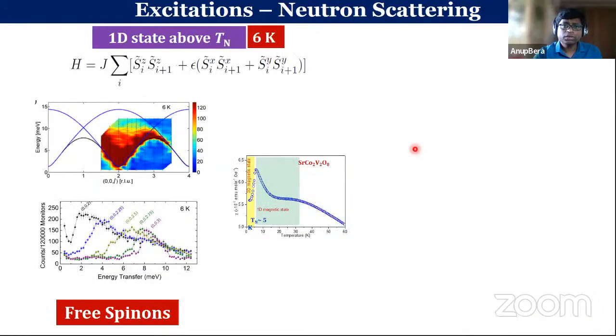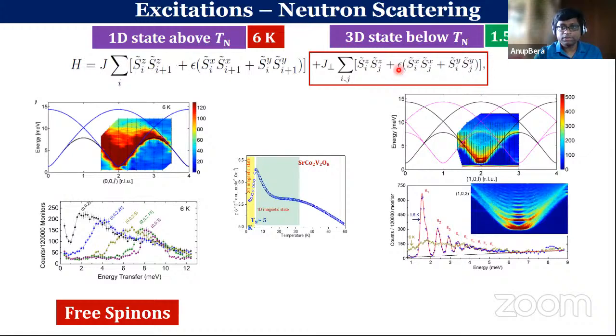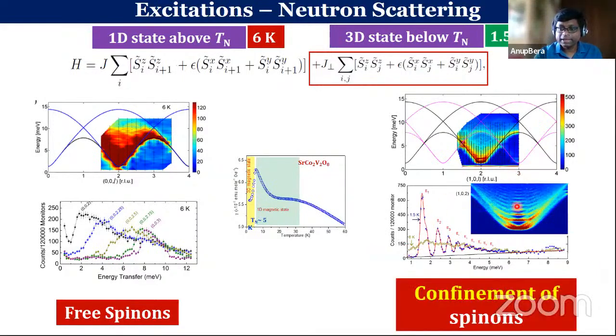Now, if we go below the ordering temperature, in the 3D ordered state at 1.5 Kelvin, we are adding one more term, which is the coupling between the chains. Immediately we see that the broad, diffuse continuum is no more a continuum. It becomes a nicely excited state with many energy states, which appear due to the confinement of the spinon pair. If I take a cut here, I see these nice energy states going up.